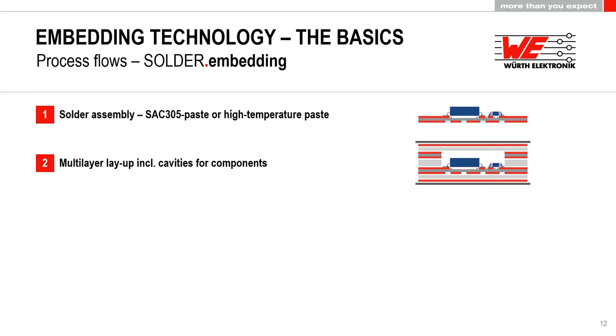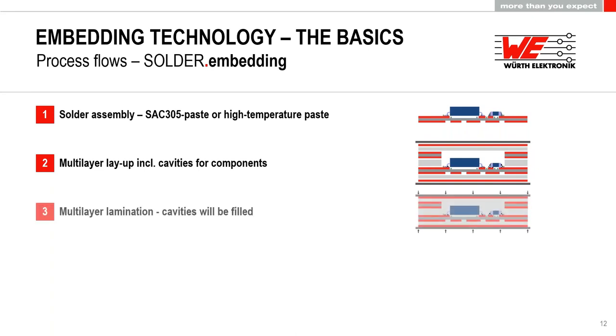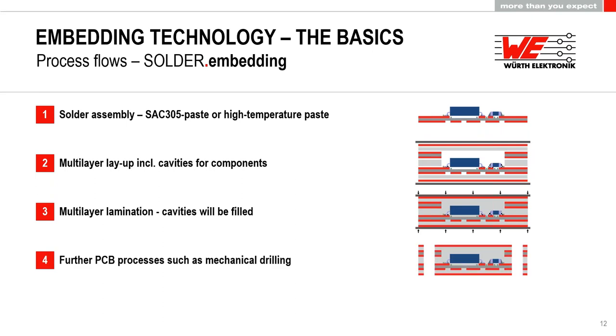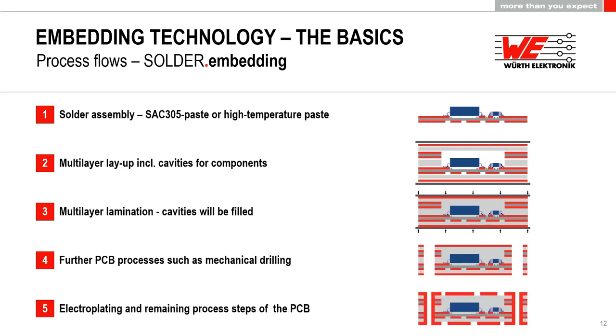So when we go to the layup, again, it's the same as on the other technologies. We create this cavity and then we increase the temperature and the pressure. We draw a vacuum and the resin is being pressed into this cavity. It flows around the components and we have the complete embedding of the components done by this. And the remaining steps basically are just the same as in any other PCB as well. We have the mechanical drillings, we have the outer layer structuring, so that we have the final PCB.